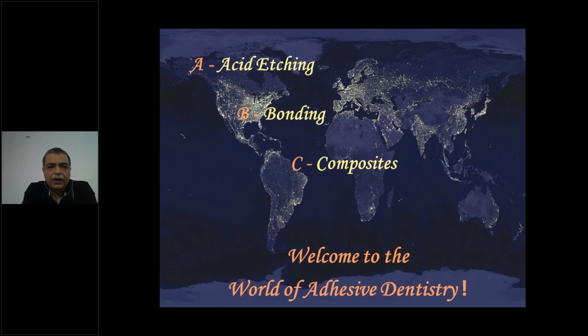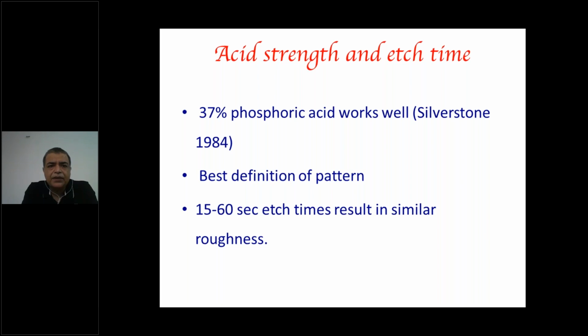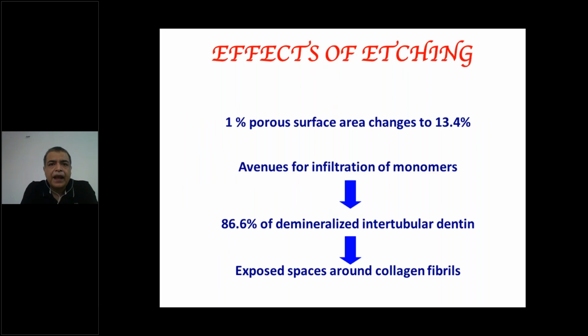So I'll talk about it in brief, and if I have some key points in between, I'll keep on giving them to you. So acid etching, we know it is simple. We generally use 37% phosphoric acid nowadays, and that gives us the best definition of pattern. And 15 to 60 seconds of etch time is sufficient, and it gives a similar amount of roughness. And what does etching do? In enamel, it increases the porous area from 1 to 13.4%, where the monomers can flow.